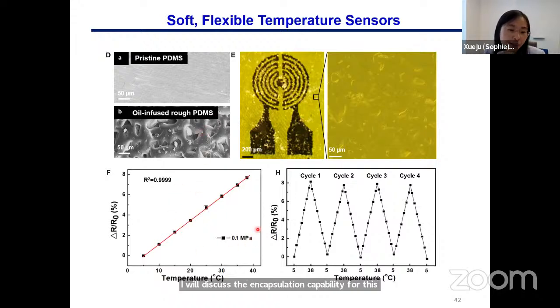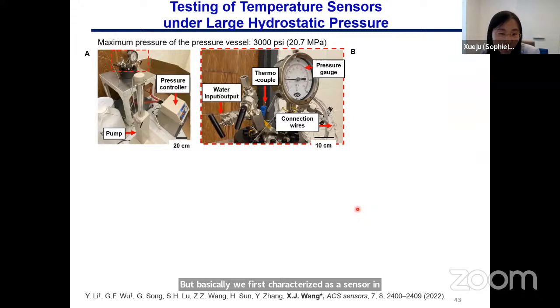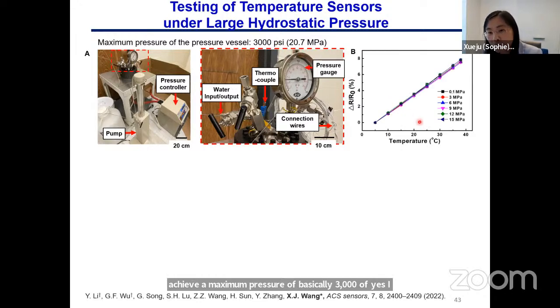But first, we characterized the sensor in ambient conditions. We can see that it has a high linearity and a good cyclic performance. To simulate the large hydrostatic pressure environment in the ocean, we custom built a pressure vessel, where we can control the pressure and the temperature simultaneously for the testing of the sensors. It can achieve a maximum pressure of 3,000 psi, equivalent to 2 kilometers in the ocean.